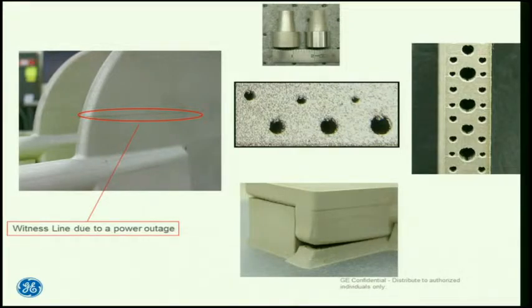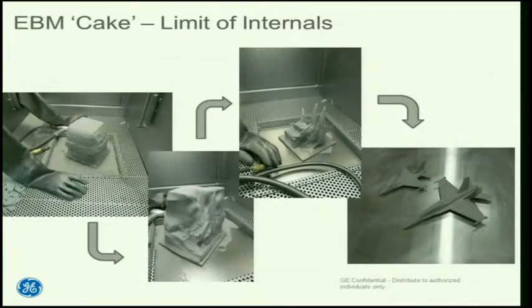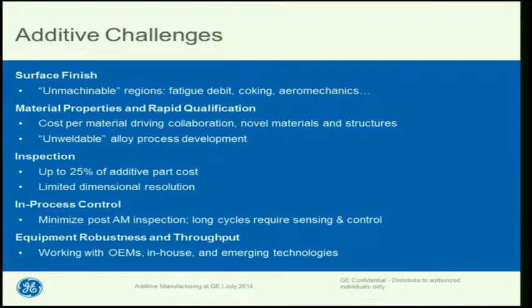You can have thick parts that pull up from the platform, and knowing how to really anchor those down becomes important. Knowing what kind of stock you need to add so that you have enough stock to post-machine to get to your tolerances. Those are all elements of the nuances of the technology. We had mentioned before in the video, I talked about the cake of parts. Here's a good example of pulling it out of the machine. We bead blast away to expose the parts. Once again, a nuance of EBM is you have a really tough time, if it's even possible, to get internal material passages, material stock and internal passages out. You have to do that in a mechanical form.